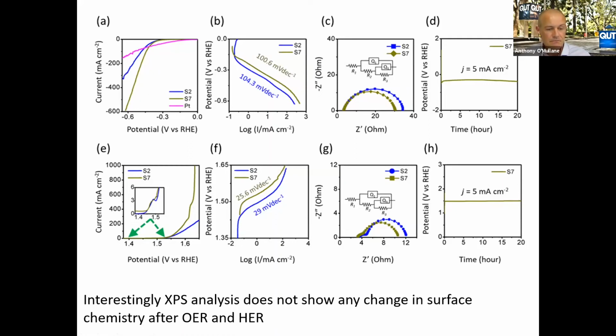We can see we have stability as well in terms of hydrogen evolution and oxygen evolution over a 20-hour period, so our material looks good. What we should note is that to get good hydrogen evolution activity, we needed the gold. If we didn't have those gold nanoparticles in there, our activity wasn't as high - it was this S2 value here. So the addition of gold was really beneficial to promoting the hydrogen evolution reaction.